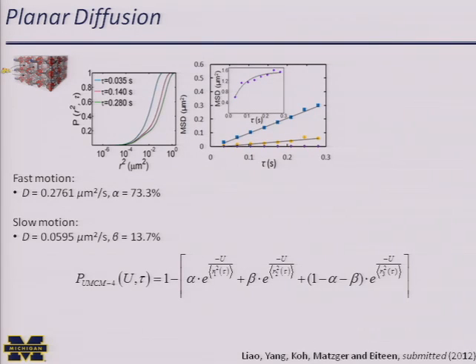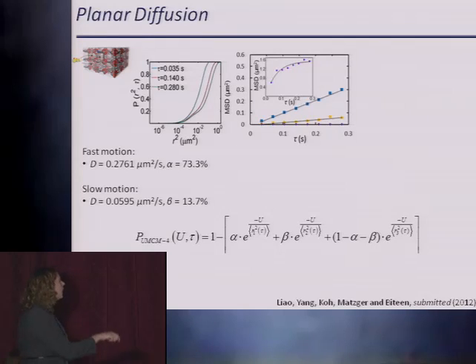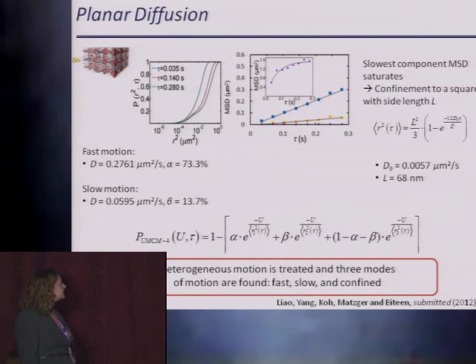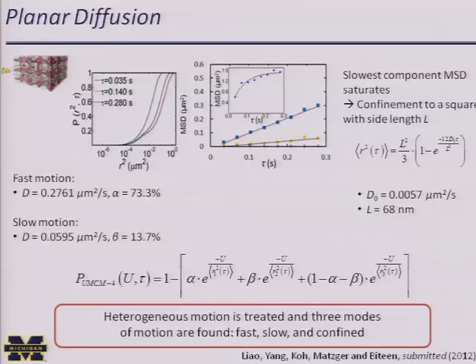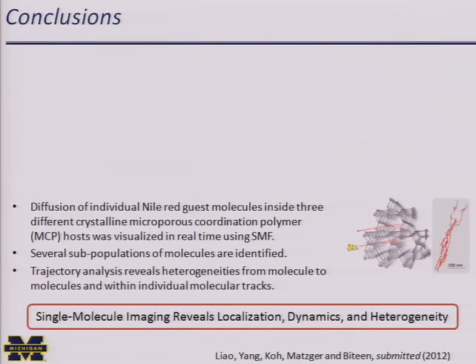Here it looks basically like 0, which makes sense for a very slowly moving particle. But if we blow it up, we see that it's not linear. It actually has a curved shape. It saturates. And this is consistent with confinement to a square with length L. So we can write out this equation where D naught is the diffusion coefficient and L is the square size. And by fitting our data to this equation, we get that there's very slow diffusion, another order of magnitude smaller, and that the lengths of these features are about 70 nanometers. So this is confinement to an area that's quite small, but actually bigger than our resolution, which here is 20 nanometers.